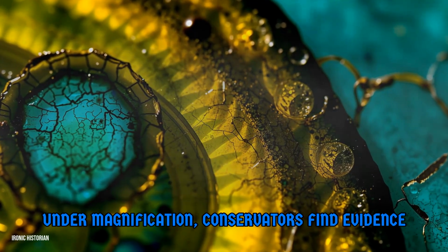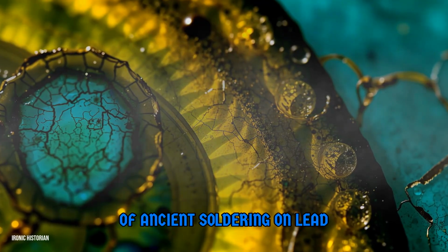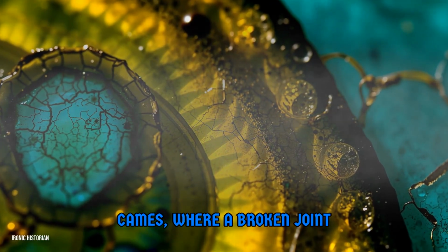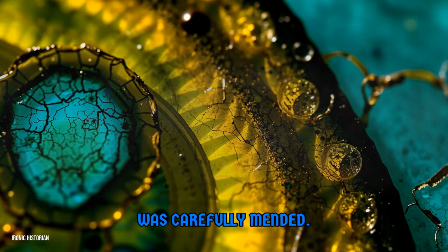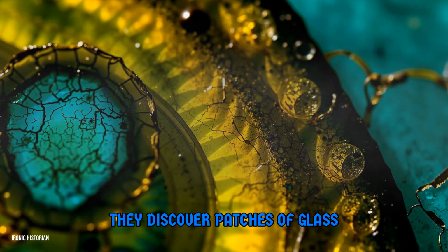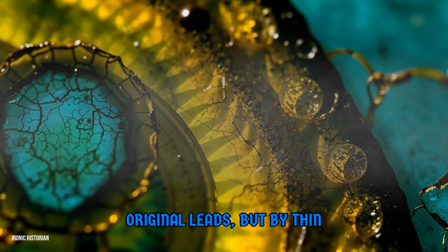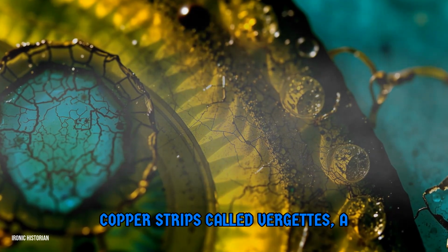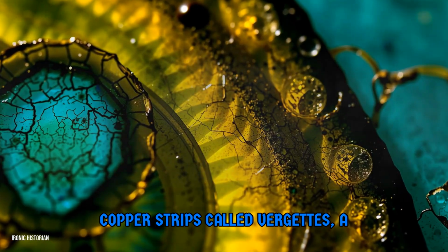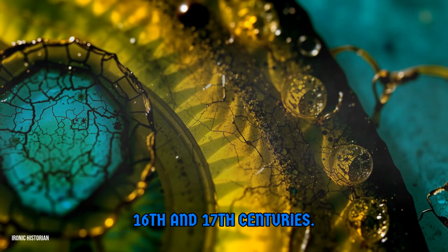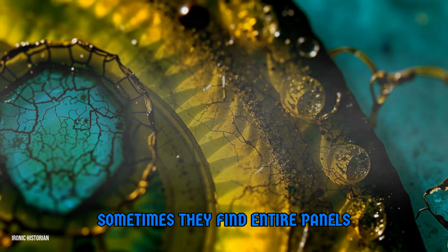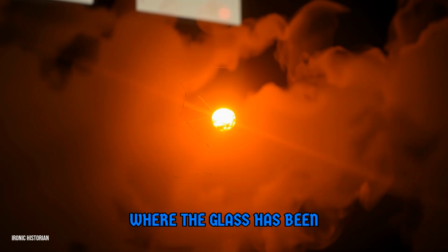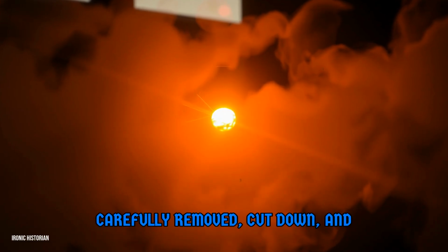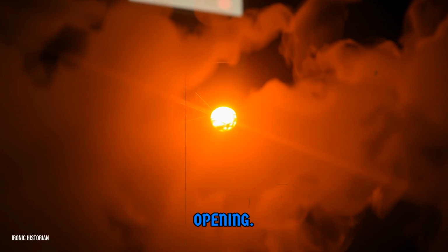Under magnification, conservators find evidence of ancient soldering on lead cames, where a broken joint was carefully mended. They discover patches of glass held in place not by original leads, but by thin copper strips called vergettes, a common repair technique from the 16th and 17th centuries. Sometimes they find entire panels where the glass has been carefully removed, cut down, and re-leaded into a new configuration to fit a changing architectural opening.